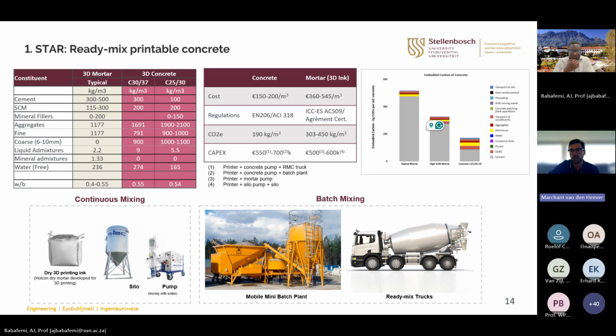But if we look at concrete versus mortar, we see that by increasing the aggregate content and reducing the amount of powders, we're able to substantially reduce the cost of this material. From a regulatory perspective, this is also very interesting because once we move from a dry bagged or pre-blended product, we move to something that the industry understands. So if we look at concrete from a European perspective, it's EN 206 that governs the supply of ready-mix concrete, and in the US context, it's ACI 318.